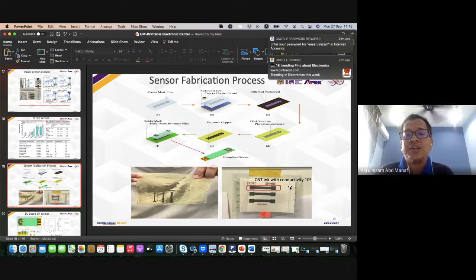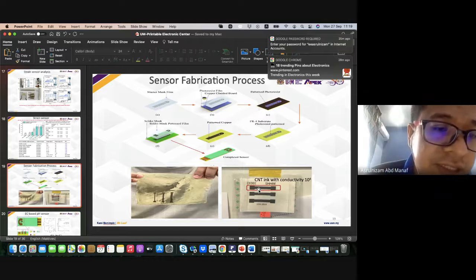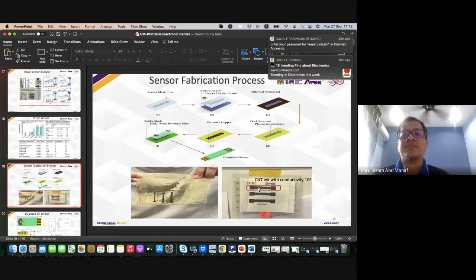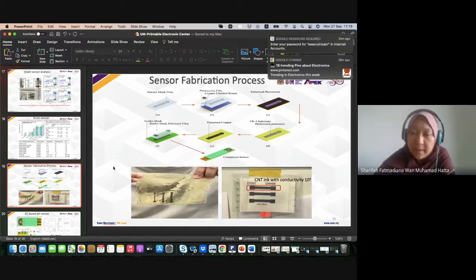To do the printing, so that it can be more connected. If a single layer can be conductive enough, that's good, because you can lower your cost and simplify the process. But in our experience, we need multiple layers to have good conductivity. Yeah. Okay.